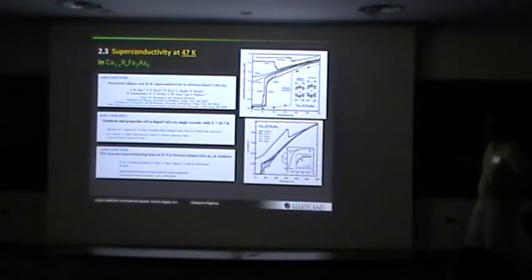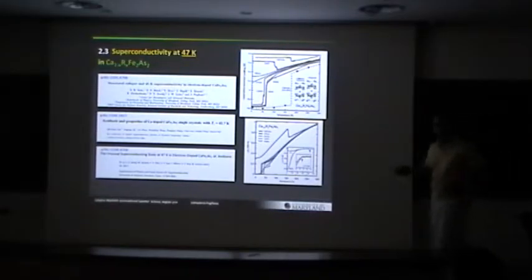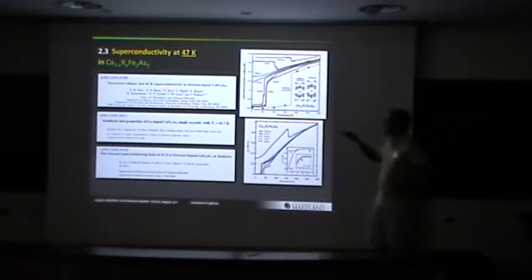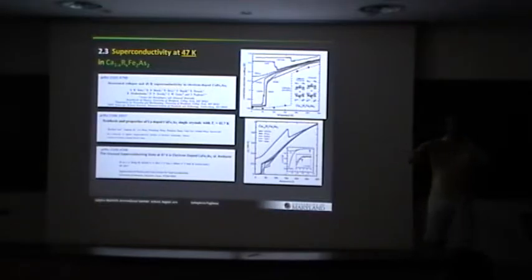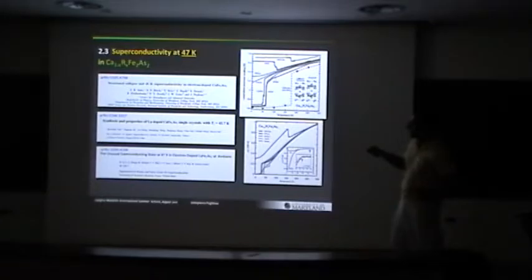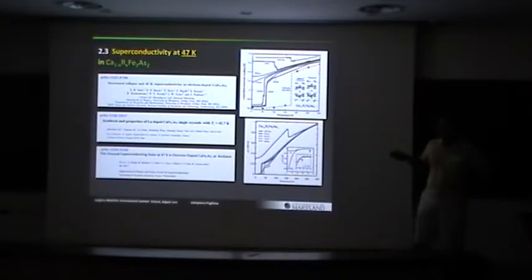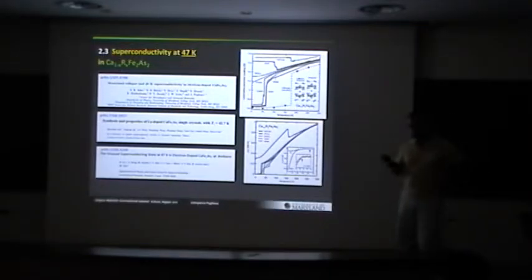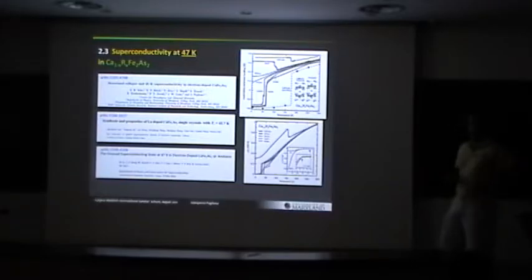So this part, I'm going to focus on our own work on this material, which is calcium iron 2 arsenic 2 substituted with rare earth. So the question came up yesterday about electron doping in the alkali earth site instead of in the iron site. And so this is an example of doing that. So you're putting in rare earth 3+ into calcium 2+. And so that's why we got interested in this study.